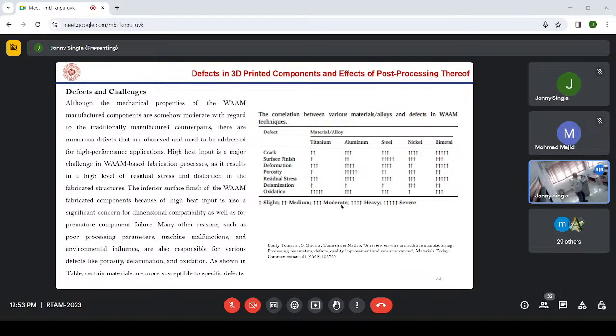So AI gives us that decision. During my talk, I was telling that you must run hit and trial experiments, so then you optimize the parameters. But AI can help to avoid those hit and trial experiments. It can directly give you certain data. Just like I am giving you data that layer thickness should be 30 micrometer, based on certain data, AI can tell us that you can keep this layer thickness as 30 micron and laser power as 150 to 200. When we study the literature, that phase can be avoided if you have an AI module incorporated into the system.